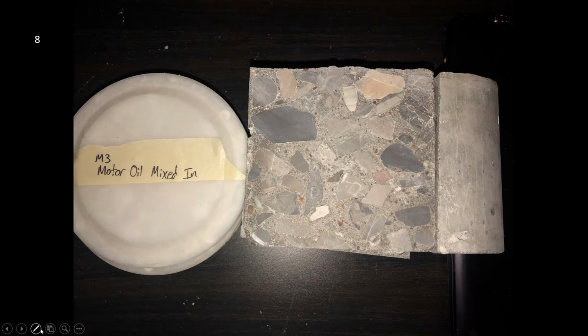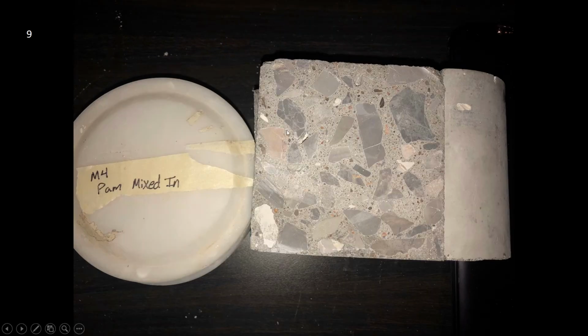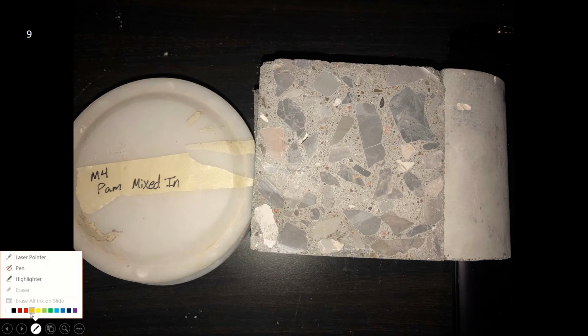This has a little effect on the surface area of the concrete, and as you can see, there are small lines around the aggregate that the motor oil just stuck itself to the aggregate. Our ninth sample is PAM mixed into the concrete. This has no effect on the surface area of the concrete, and you can't really see a difference in the cross section either.